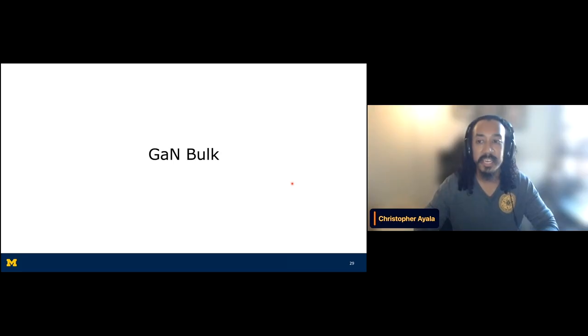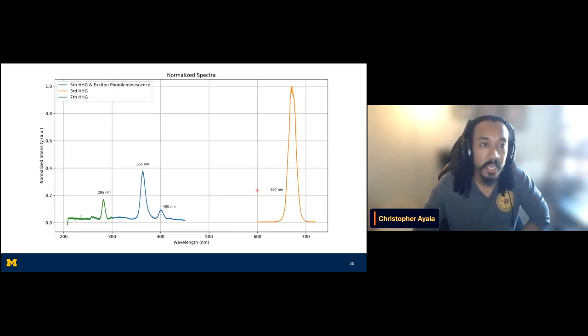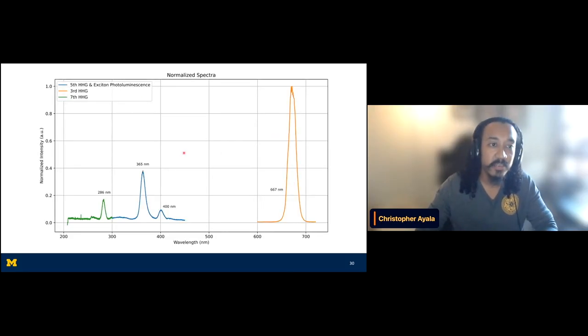So we'll first talk about this gallium nitride bulk. As you can see here, we're able to reproduce the results and see the third order harmonic, the fifth order harmonic at 400 nanometers, this excitonic response for the gallium nitride, which is at about 365 nanometers, and a seventh order harmonic at 286. To take into account, I was not able to fully see into the lower end of the UV spectrum, and this is most likely the case due to our device limitations that we have here.